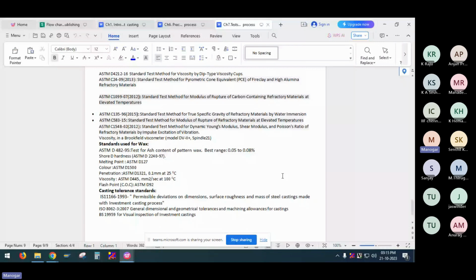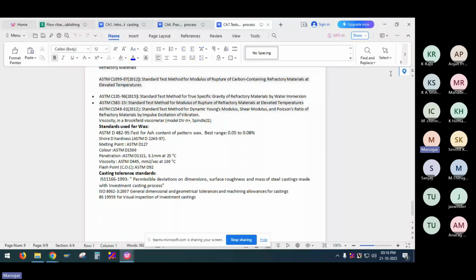Standards used for wax: ASTM D482 for ash content, Shore hardness test, melting point D127, color penetration test ASTM D1321, and viscosity and flash point. Casting tolerance standards used in the investment casting process are IS11166-1993 and ISO 8062 for general dimensional tolerance, and BS 19959 for visual inspection of investment castings.